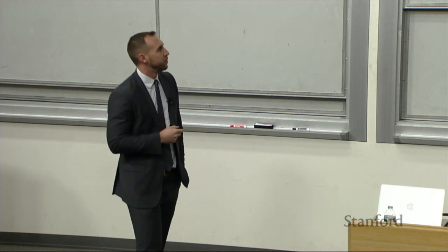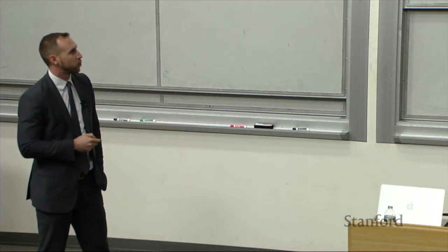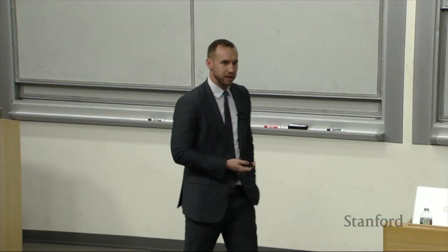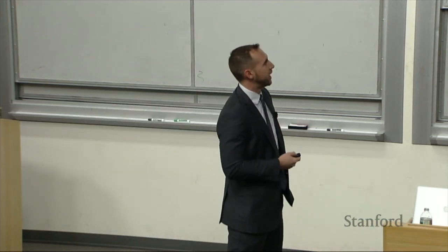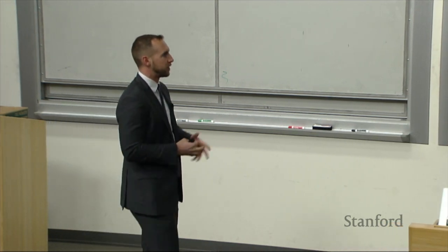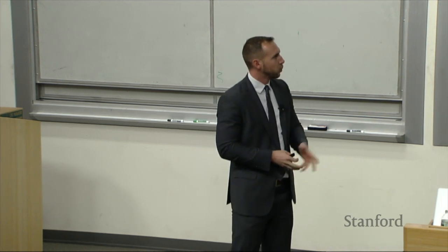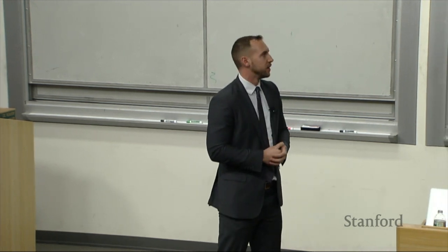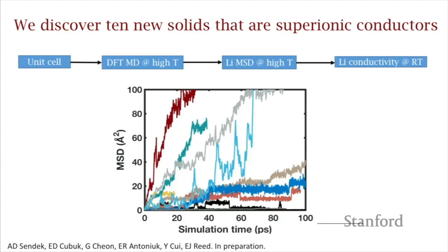So this is the long and short of it: of those 21, we found about half of them, 10 of them, showed really exciting levels of lithium-ion conduction at room temperature. And we found this through doing these physics-based simulations. We're a computational group, so this is kind of our wheelhouse, although we have been working with some experimental groups as well to do that sort of testing. But the approach we take is to simulate density functional theory molecular dynamics simulations, which is where you basically set a temperature and you just let the atoms rattle around, and we're watching for lithium motion.